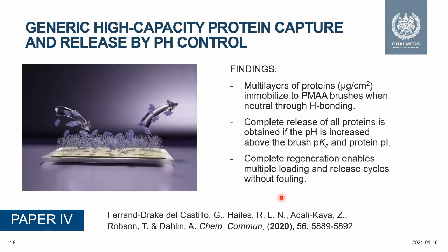In conclusion of paper 4, we can state that polyacidic brushes in neutral state have a large capacity to bind proteins by non-electrostatic interactions. This is a new method for protein immobilization that is distinctly different compared to conventional immobilization by electrostatic attraction. Importantly, complete release of proteins was achieved, enabling multiple capture and release cycles without fouling. The use of polyelectrolyte brushes in this way makes them highly appealing for applications such as protein purification.